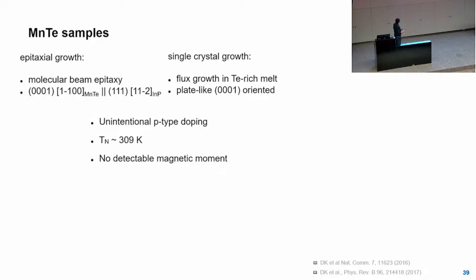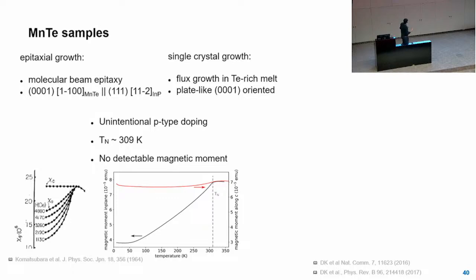right stoichiometry, and we provide a bit of heating so that there's enough energy for the crystal to grow properly. But you might understand more of that than me actually. So we are just kind of simple physicists shooting the stuff on it, and it somehow turns out to work. And in addition, we also have these single crystal growths where we just weigh the elements together. We melt it, we let it cool down slowly, and it also crystallizes. And then we just check its properties.